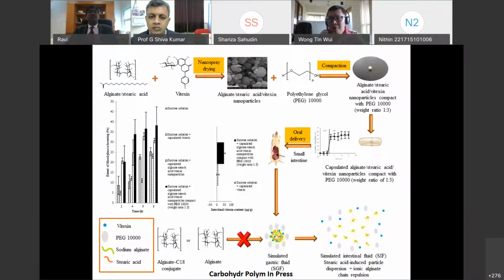What we have found is that the polyethylene glycol functions very well to reduce the vitexin release to almost 0% in the gastric region. Upon the compact entering the intestinal region, you can see a surge in drug release. The small molecule vitexin is very hard to control, right? But in our case, we are able to reduce the release in the gastric phase to 0% and enhance the release in the intestinal region.